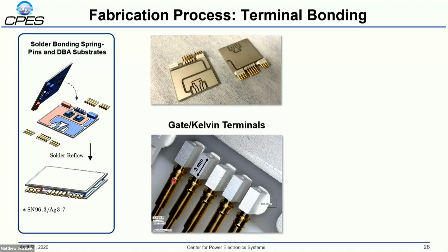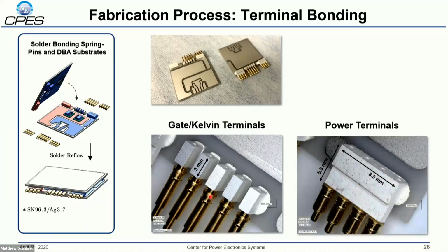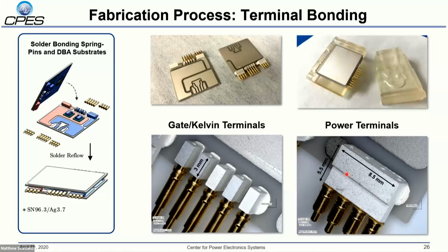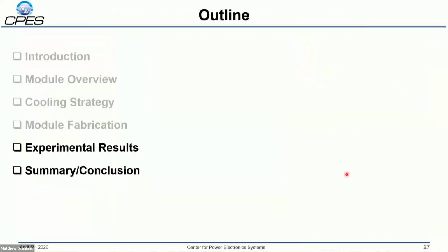There's a commercially available spring pin we get from Mill-Max and a custom molybdenum post. So the molybdenum post is sintered down to the substrate, and then the pin is soldered into the post. So that's what the low current gate and Kelvin terminals look like, and then the larger power terminals to actually conduct the drain current. And once the terminals have been attached, the sandwich structure can be assembled and then potted into the housing as you see in the top right.